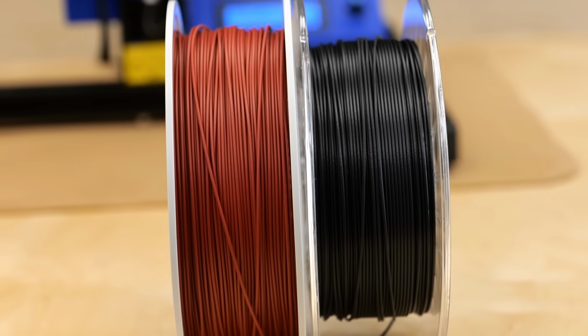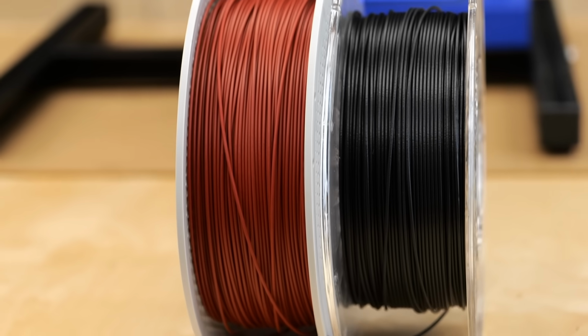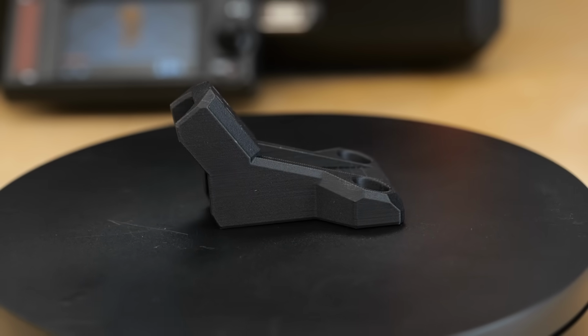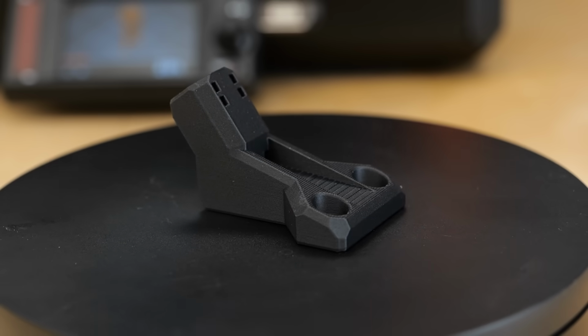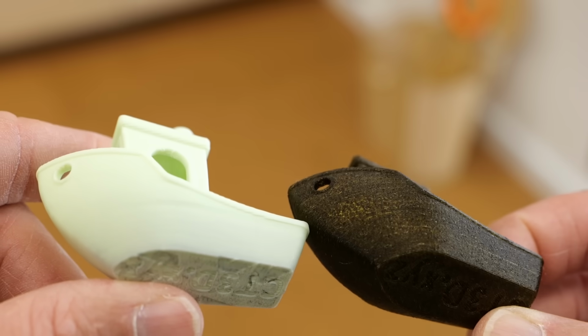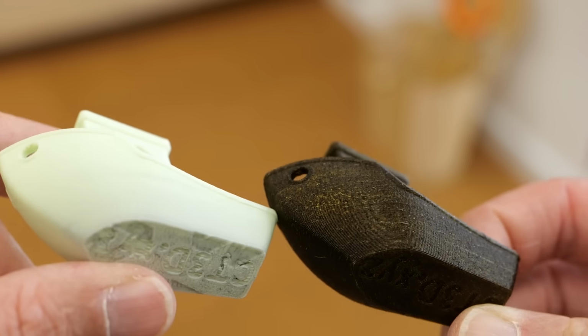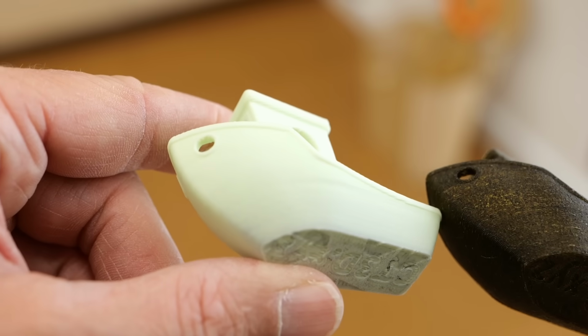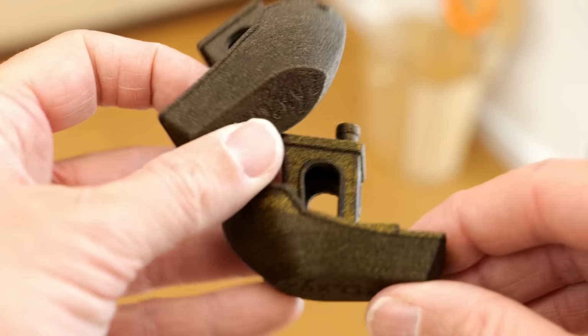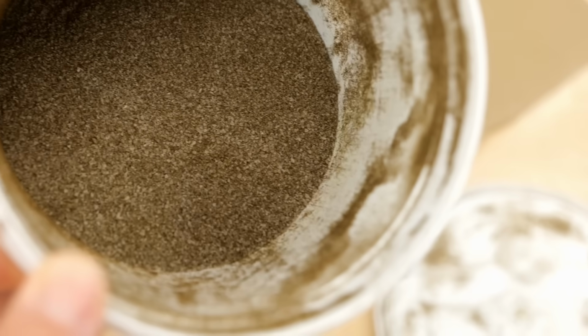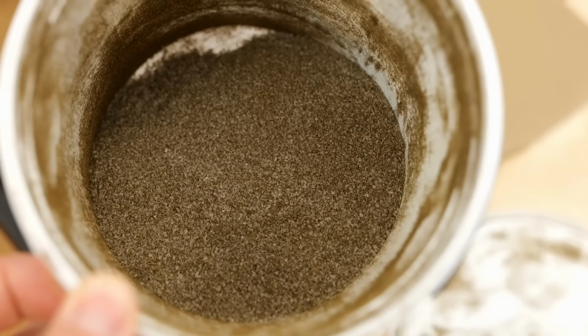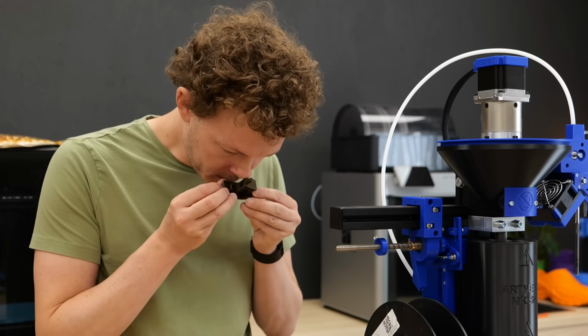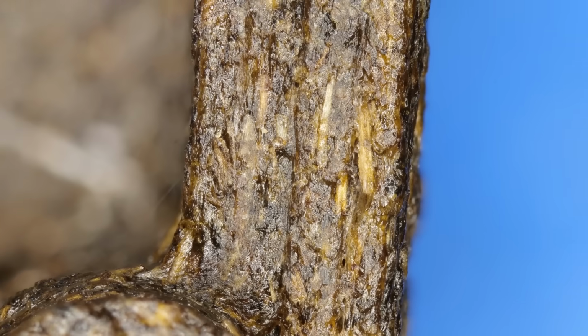Some might say that this is a bummer, but even many carbon or glass fiber reinforced materials don't add significant strength. They primarily increase stiffness and improve properties like dimensional accuracy, or simply make the parts look nicer. And I think I also achieved the last 2 points with my PLA. Getting rid of or at least reducing the bowing on the benchy indicates that the material shrank less during printing, and the look and feel of the parts are really nice. Again, using in my case up to 20% less plastic because it was replaced by cow poop. And if you're worried about odors, the parts don't smell a single bit. Everything was sanitized during drying and extrusion, and the fibers are perfectly embedded into the polymer matrix.